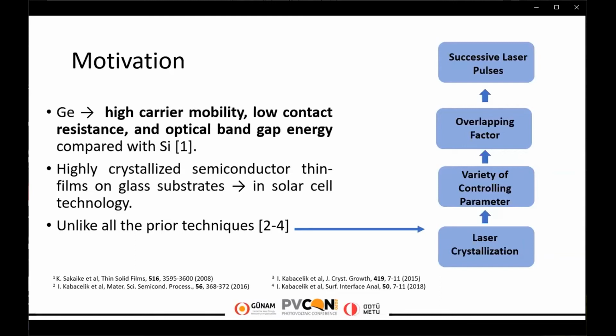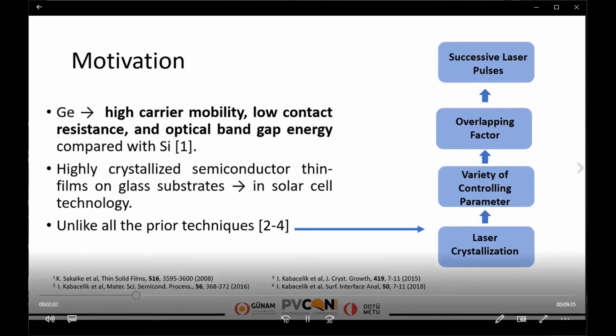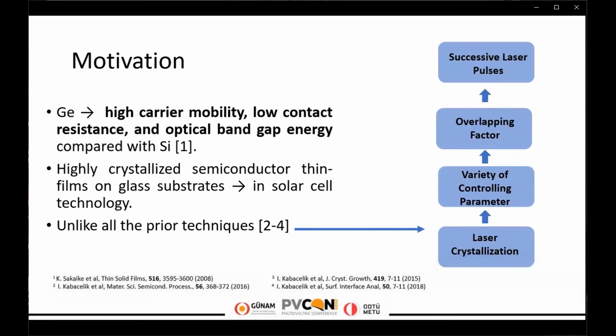Different techniques have been applied in order to produce polycrystalline germanium films, such as solid phase crystallization and metal-induced crystallization processes. Unlike all the traditional techniques and thermal processing, pulse laser processing offers versatile control of the phase transition of the material from amorphous to crystal in a short duration. The main advantage of laser crystallization is to adjust the rapid cooling by changing the overlap ratio of the successive laser pulses.